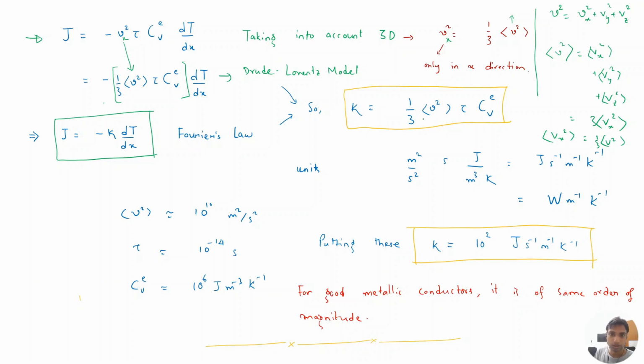So, this is the expression, and it has the units of watt per meter per Kelvin. Typically in a particular material, this v square is of the order of 10 to the power 10 meter square per second square, tau is of the order of 10 to the power minus 14 second, and the electron specific heat is 10 to the power 6 joule per meter cube per Kelvin. If you put all this in this expression, what you get is kappa equal to around 100 joule per second per meter per Kelvin, which is of the same order of magnitude for metallic conductors. So the thermal conductivity is also explained very well by the Drude-Lorentz model.